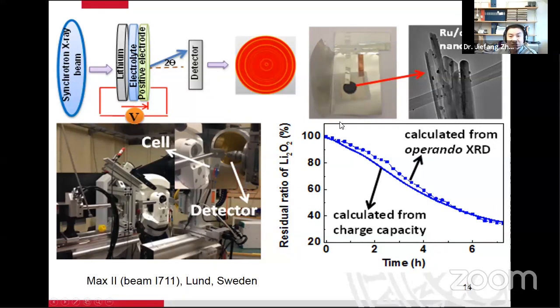So this is our cell. At the beginning, we used a coffee bag cell. It's also called a pouch cell. This is our sample. We have two poles to the external circuit. By the way, inside the pouch cell is a polymer layer, and outside is aluminum. So it has a very good sealing effect, and it can stand quite a long time, for several months.